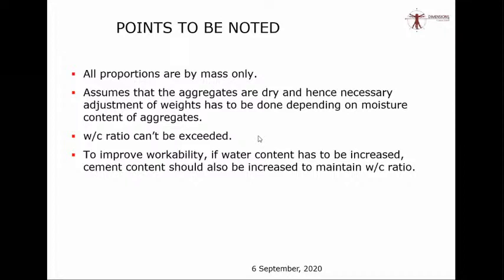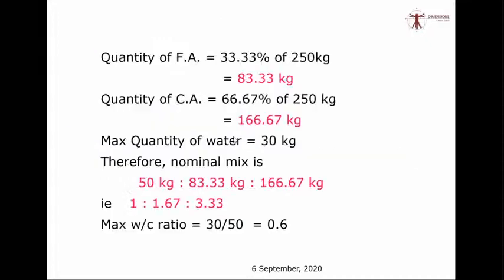It is not by volume. It assumes that the aggregates are very dry. If it is having moisture, then the necessary weighing adjustment has to be done, which means if I say 83.33 kg, and supposing it is moist, probably 3.33 kg is only water. I only have 80 kg of sand. So this should not happen.